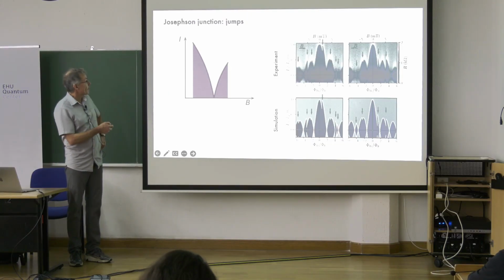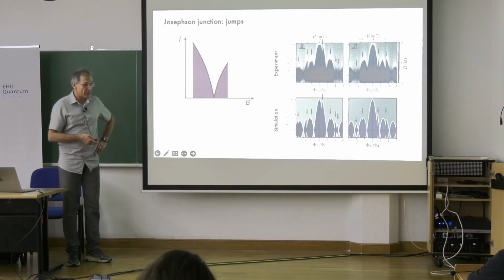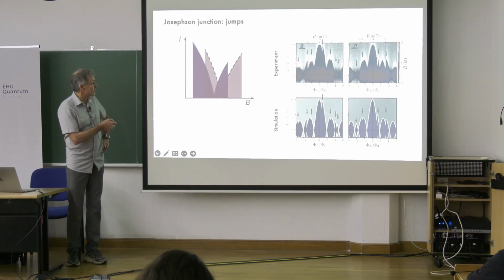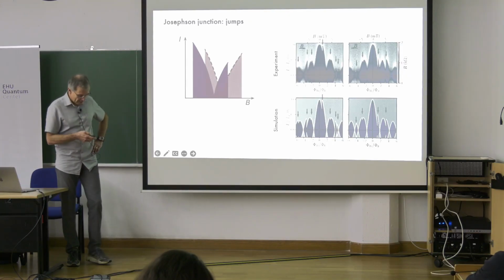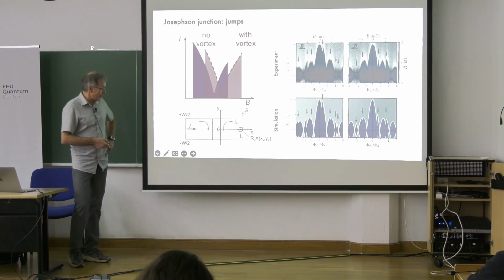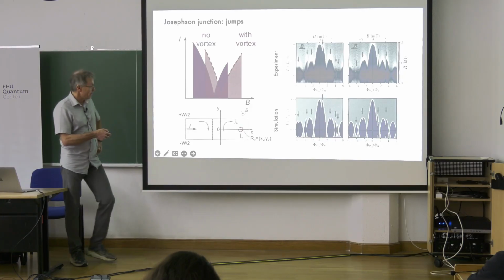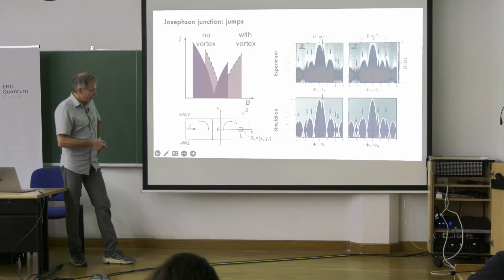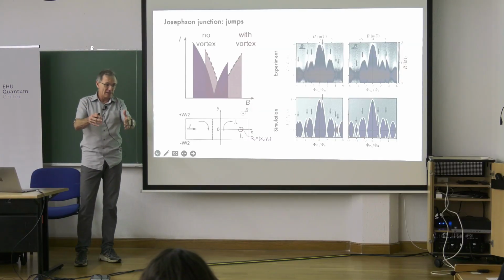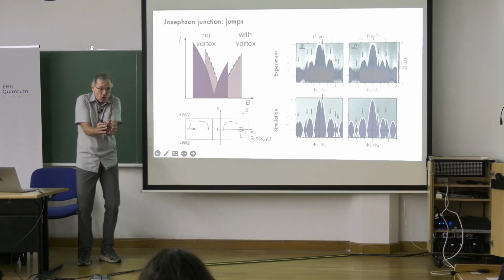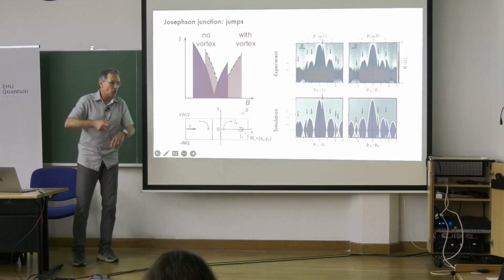So what do we have? Without a vortex, let's assume we have this Fraunhofer pattern. And with a vortex, we have such a Fraunhofer pattern. It's important to realize that this pattern with a vortex always shifts to the right. This is because the current which is produced by the vortex is in the opposite direction to the Meissner current. Because the Meissner current screens the field from outside, and the vortex current screens the field of the vortex from inside. So they have to flow in opposite directions.